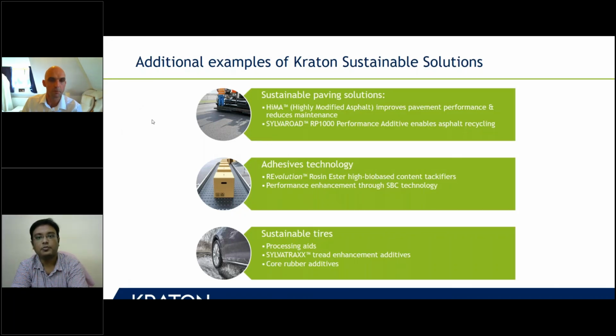Well, just very briefly to wrap up, a couple of other sustainable solutions, a little bit outside my direct working scope. We have the highly modified asphalt, which improves pavement performance and reduces maintenance. So it's a styrenic block polymer added to bitumen, and it's basically giving elasticity to a road. We have some Silvaroad RP1000 performance additive that helps recycling of asphalt. In adhesives, we have our Revolution rosin ester, which has a very high bio-based content as a tackifier. You can enhance the performance through a styrenic block polymer technology. And I mentioned already briefly our Sylvatraxx tread enhancement additives in tire. They help with rolling resistance and grip balance. And there are some core rubber additives that we have as well as processing aids.